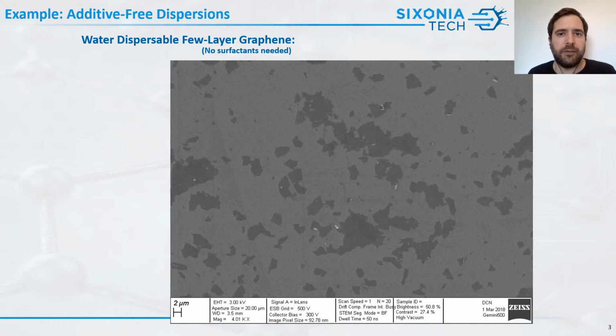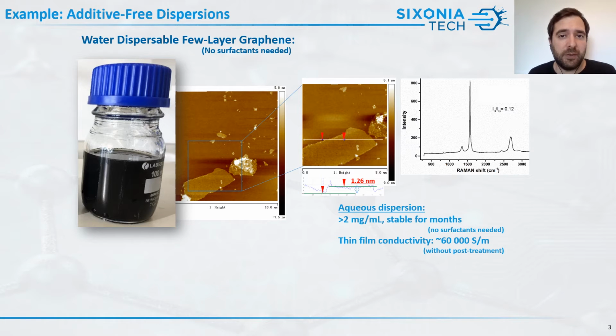So if you look at our graphenes, there's really one thing that distinguishes them from other materials, and this is what I said already: they are high quality materials which are very processable. What you're seeing here is the SEM image of some graphene flakes that are actually dispersible in water without the use of any surfactants. But still, if you look at the Raman, for example, you can see that in the center of the flake you have a very, very low level of defects, and the conductivity of these materials is really very high. Up to 60,000 Siemens per meter is something that you do not easily find in other graphene materials.